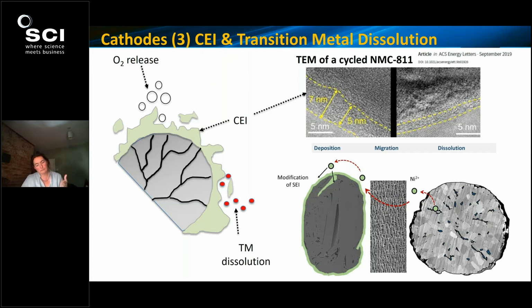And so as a result of this, with the high nickel materials, which do also suffer moisture sensitivity, passivating these surfaces before they're actually operated, or adding electrolyte additives to try to pin or mitigate this transition metal dissolution, is a very popular current area of research.